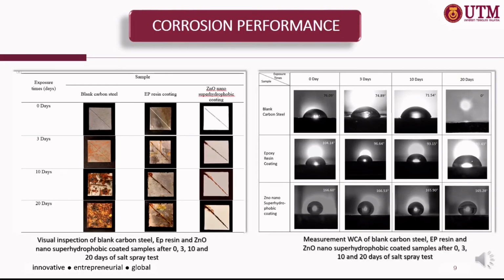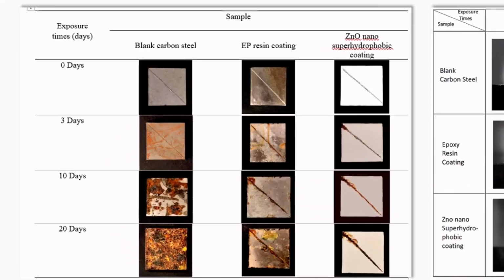For corrosion performance, all the samples underwent salt spray testing with the ASTM B117 testing standard to mimic a corrosive environment for 20 days exposure time. Samples were checked at 0, 3, 10, and 20 days. The images were recorded as well as the water contact angle. As you can see in the figure table, after 10 days, an excessive amount of corrosion product can be seen on the uncoated sample surface. However, the amount of corrosion on top of the zinc oxide nano-coated surface was very small compared to the EP resin surface. After 20 days, the uncoated sample shows an extravagant amount of corrosion product built up compared to the EP resin and zinc oxide nano superhydrophobic coated surface.